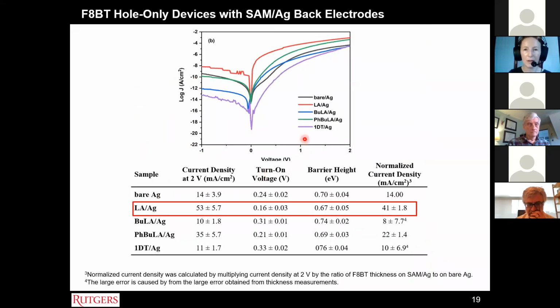So in the devices, we found that the lipoic acid on silver showed the best performance as opposed to these modified compounds. And you can see, for example, the barrier height is reduced compared to bare silver, as well as lower than the other cases, and also the 1-decane thiol, which is sort of the control self-assembled monolayer. You can also see that the current density has increased very significantly for the lipoic acid compared to the bare silver. The turn-on voltage is also reduced. And then second best is the phenylbutyl lipoic acid compound. You can see that that's also been reduced compared to bare silver and is almost as good as the lipoic acid case.